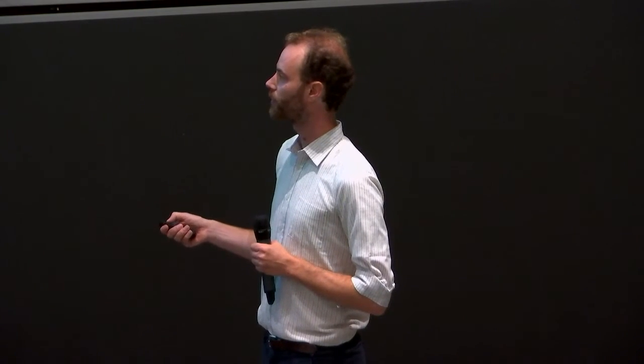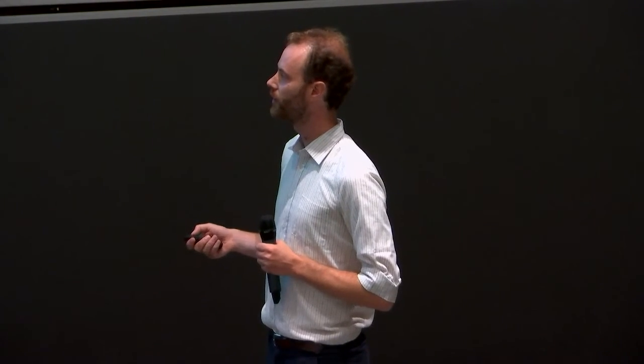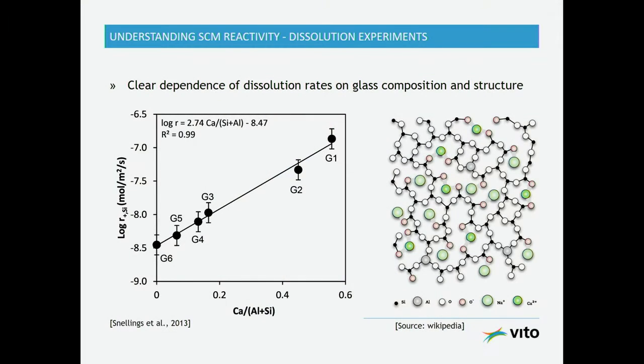What you already need to see here is that this is normalized by specific surface area. This, for instance, does not mean that silica fume, which is plotting around here, or would plot around there, is less reactive as a material than a slag, but silica fume is also an order of magnitude finer, has much more specific surface area. So it would move up here if you would not do the normalization by the specific surface area.